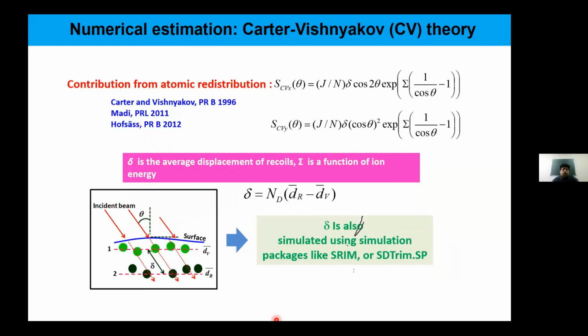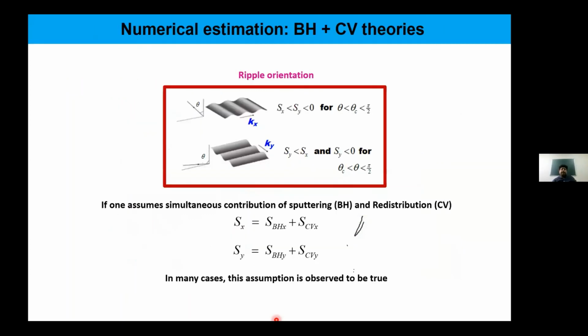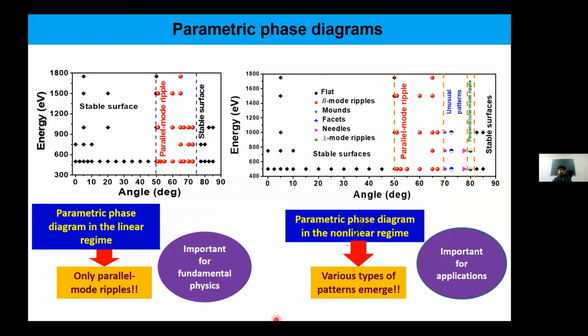And this is how one calculates delta, the recoil, from the recoil cascade. So if one assumes simultaneous contribution of sputtering as well as atomic redistribution due to ion-induced diffusion, surface diffusion rather, then it is found that pattern formation can very easily be explained in most of the cases.